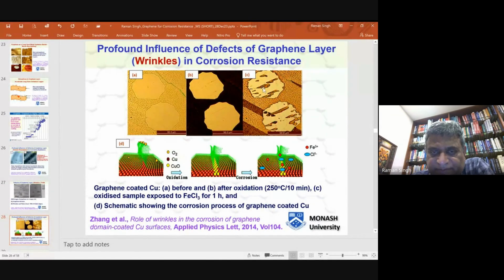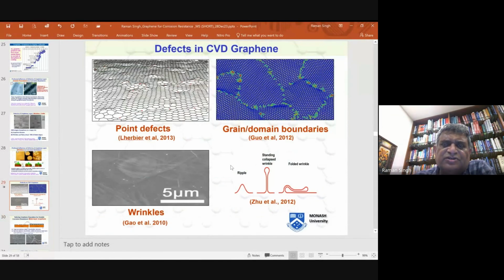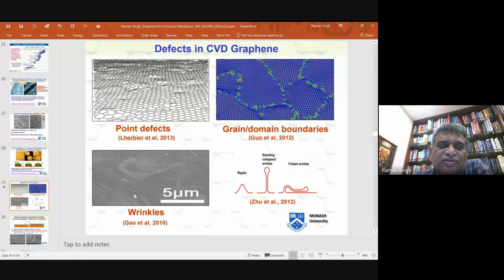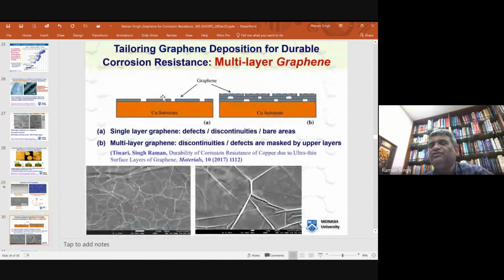People showed this. So what I showed you is that graphene can have problem of this kind of inter-domain boundary. Corrosion can happen at that place. Corrosion can happen at wrinkles. There is another problem. There can be point defects. In place of hexagonal structure, you can have pentagonal or heptagonal structure, and those are point defects. And those are also not very good for corrosion resistance.